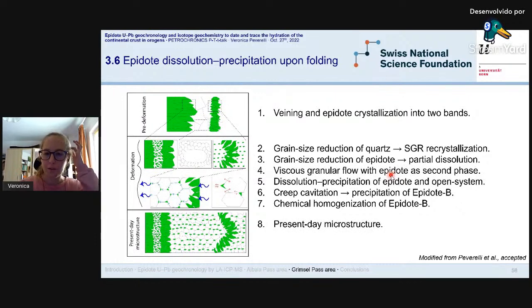And finally, we have the present-day microstructure, which allows us to propose the occurrence of epidote dissolution precipitation. And the reason why this is important is that dissolution precipitation is a very important aspect of viscous granular flow. And viscous granular flow was the dominant deformation mechanism active in the alpine shear zones in the study area. And the other important aspect is that epidote is a hydrous mineral. And so when we dissolve epidote, we basically recycle previously stored fluids.